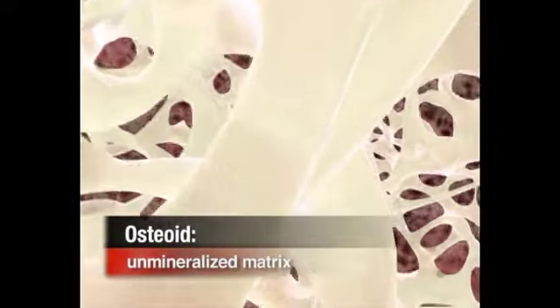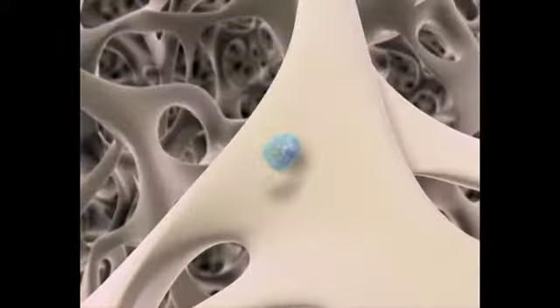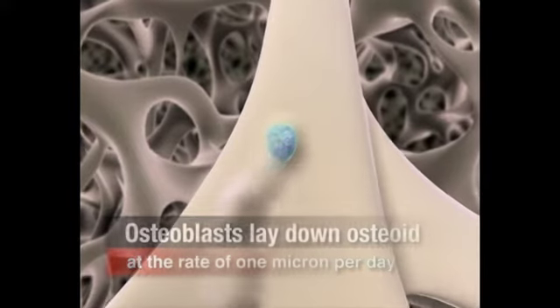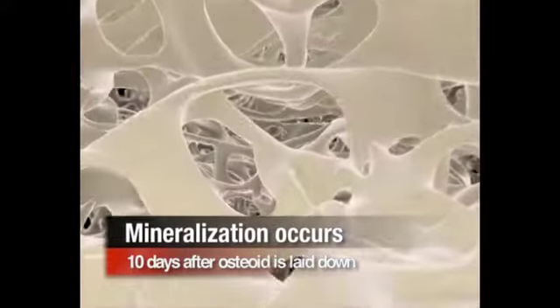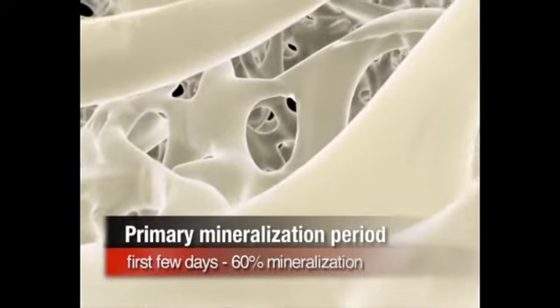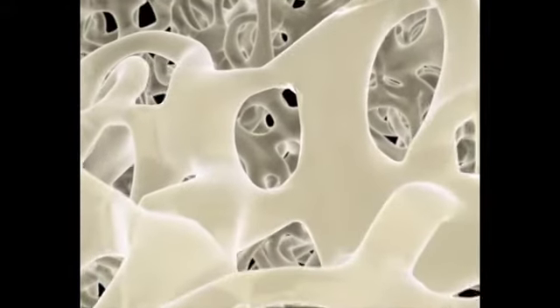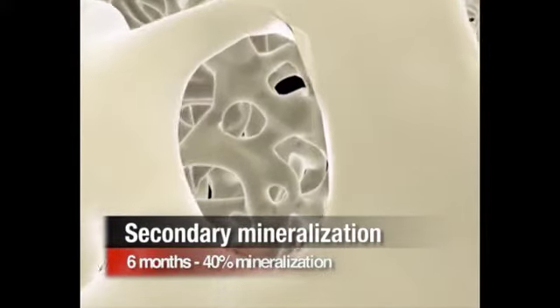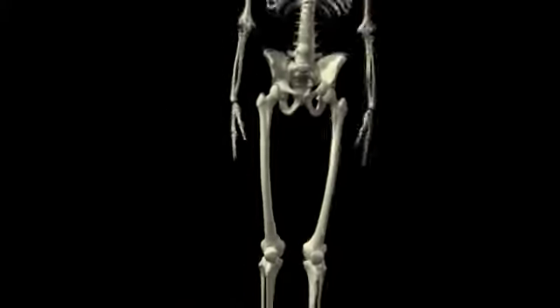The initial, unmineralized, or uncalcified matrix is called osteoid. Osteoblasts lay down osteoid at the rate of about 1 micron per day. After osteoid is laid down, there is a mineralization lag time of about 10 days before mineralization occurs. 60% of the mineralization occurs during the first few days, the primary mineralization period. During secondary mineralization, the remainder of the mineral is deposited at a decreasing rate over the next 6 months. When mineralization occurs, the tissue is called bone.